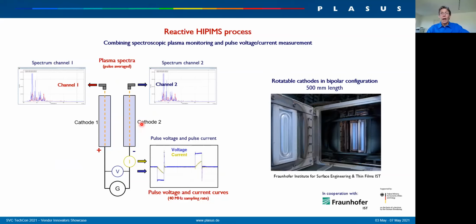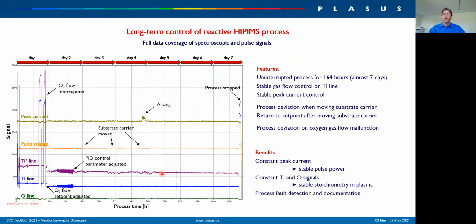Going on to a last application for sputtering processes, for reactive high power impulse processes, we have done a collaboration with the Fraunhofer IST, and here I wanted to show you how we integrated the pulse curves of voltage and current into our process control system. We monitored the two cathodes of this dual cathode application, each cathode with one channel, and in addition we picked up the pulse curves of voltage and current. We set up monitor tracks for the different lines. In this case, this was a titanium target, and we set monitor tracks for the voltage and for the peak currents. And this is shown here.